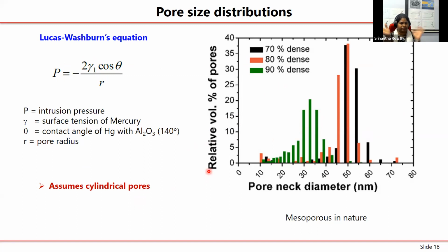It's quite like a network. So that means this equation, whatever values that you're actually measuring, are not the precise values that the sample has. But then there are no better models to bring your measurements to your porosity values, so we had to use this approximation. Certainly, if somebody tries to develop a better model for this sort of random network porous blocks, it is a very good scientific contribution.